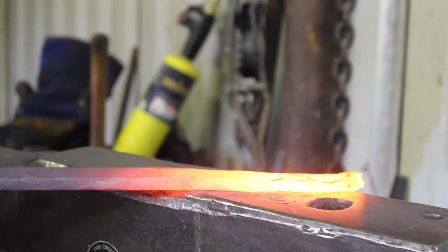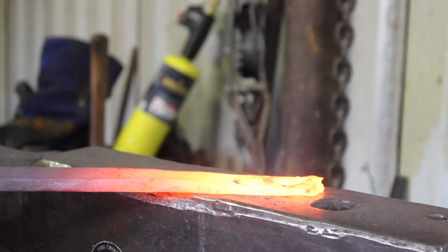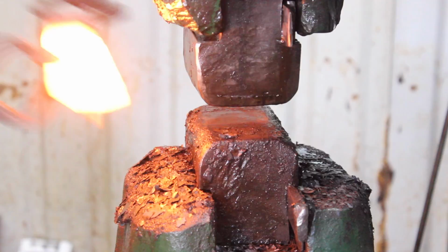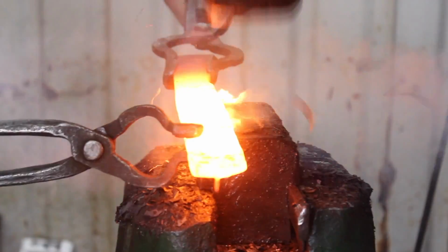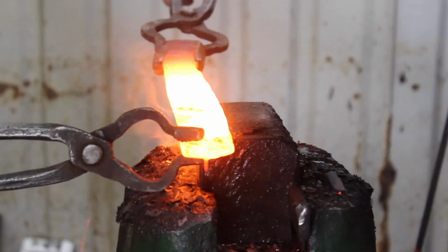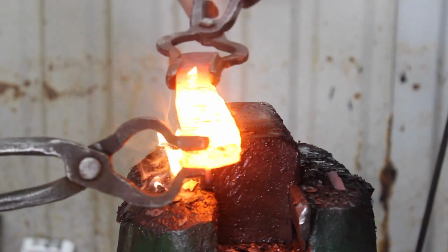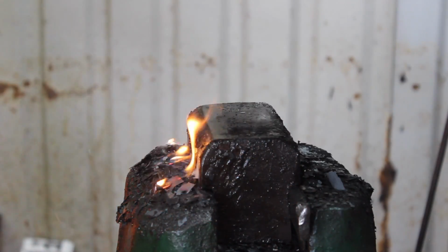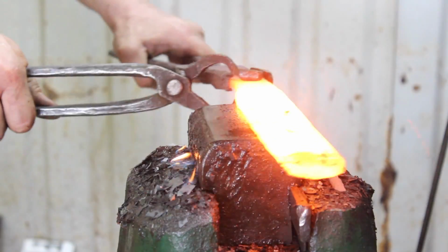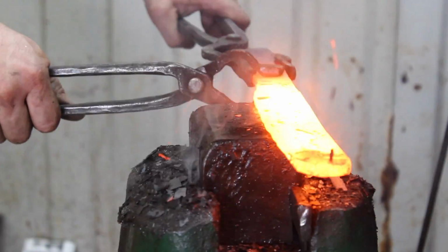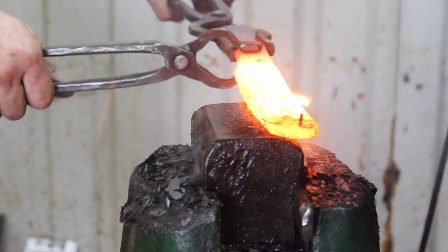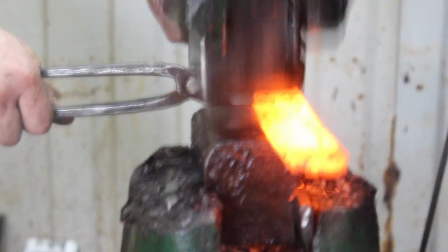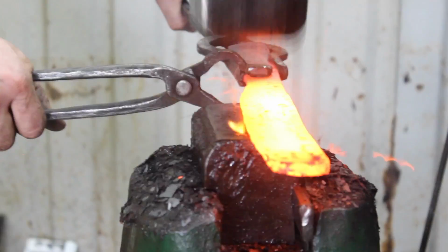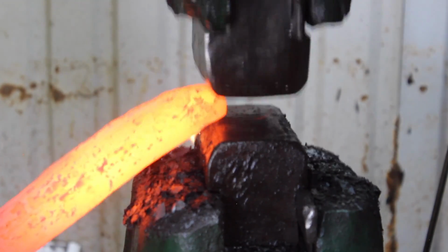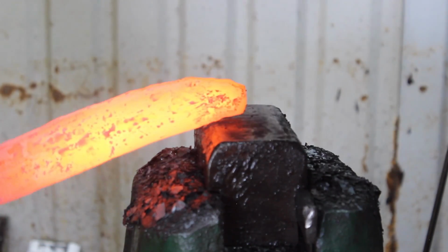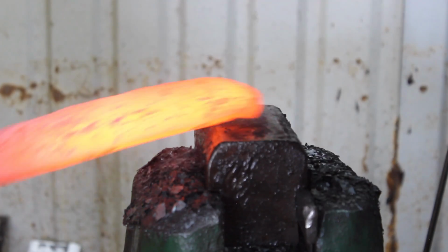The tang for the handle on this blade is tapered a little bit, and I'm using my straight peen hammer to spread that out a touch. And here I'm starting to forge in the bevel, which I'm going to do not as far as I would on a regular mono steel knife, but I do want to forge it in somewhat. That's going to minimize the amount of grinding, but also it's going to bring the Damascus cladding on our finished blade down closer to the edge.